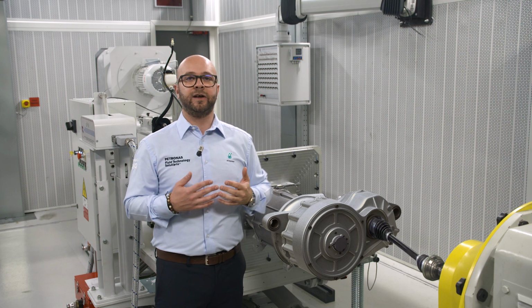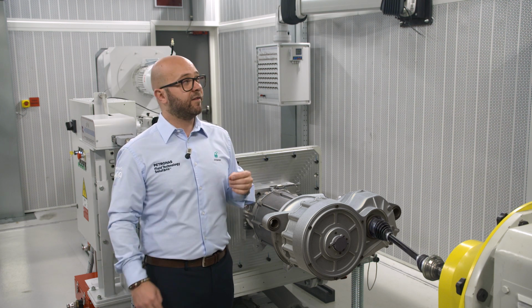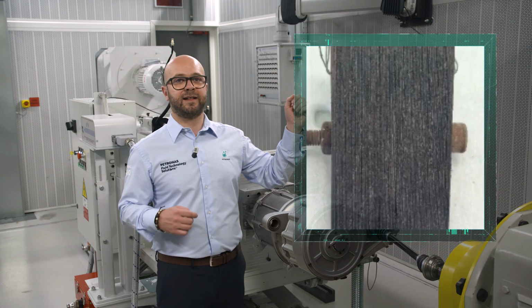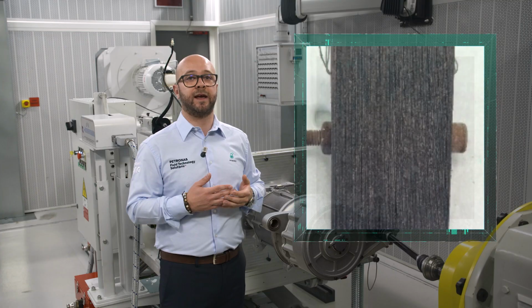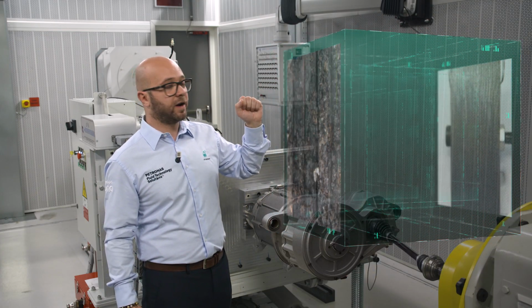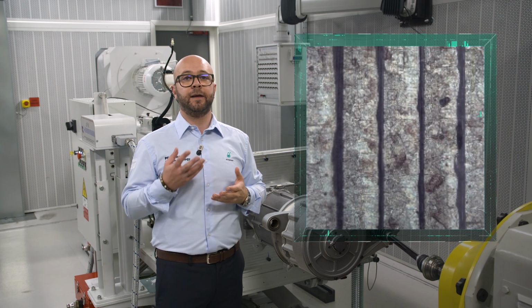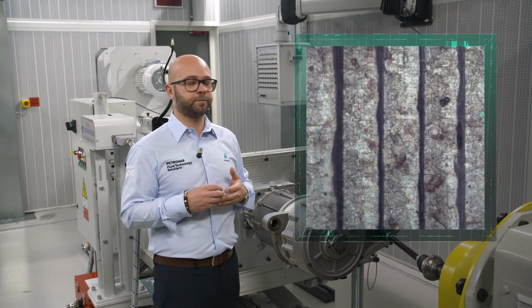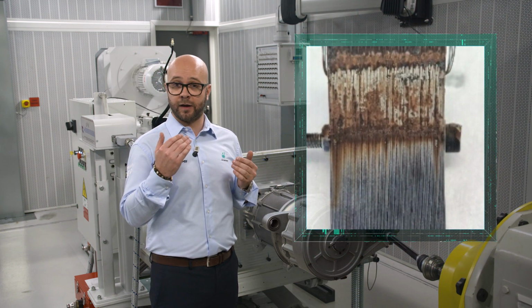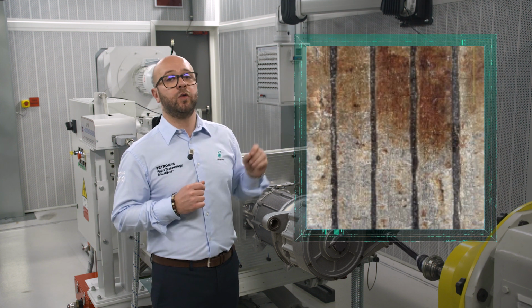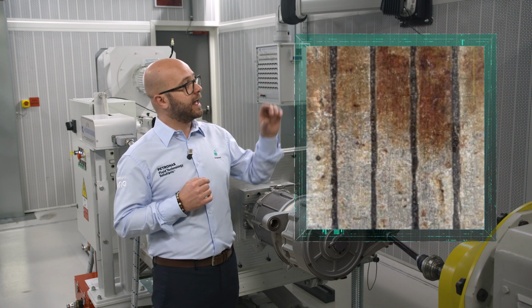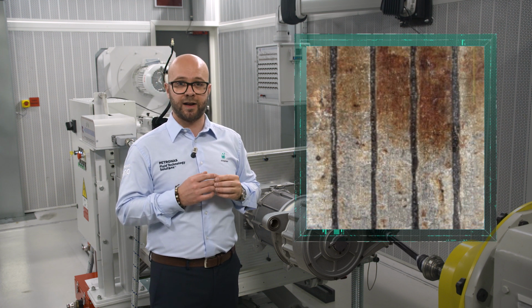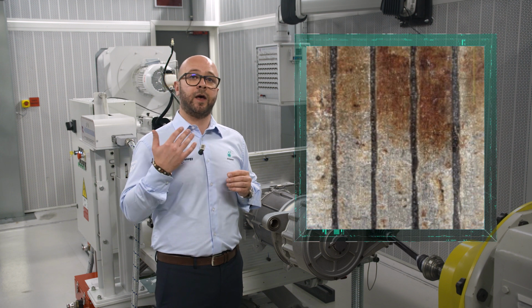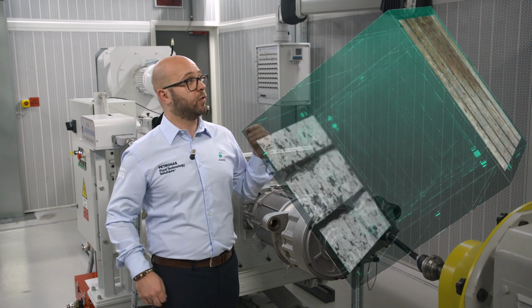Moving now to configuration A, the result is very different according to the type of exposure. We have a dark surface which characterizes the part exposed to the vapor, while the part exposed to the liquid phase is still clean with a bright look. Moving now to the part exposed to the interface, we can see two different conditions of the surface: a more damaged part, which is exposed to the vapor, and a bright part, which is exposed to the liquid.